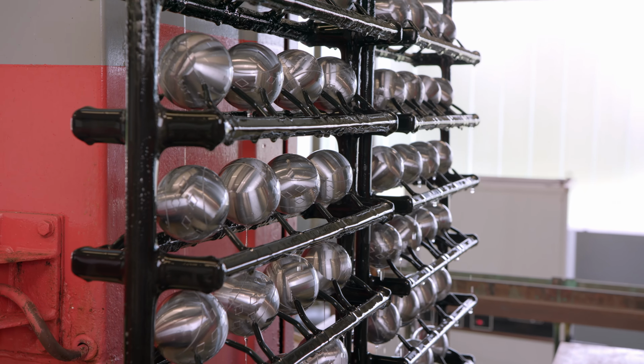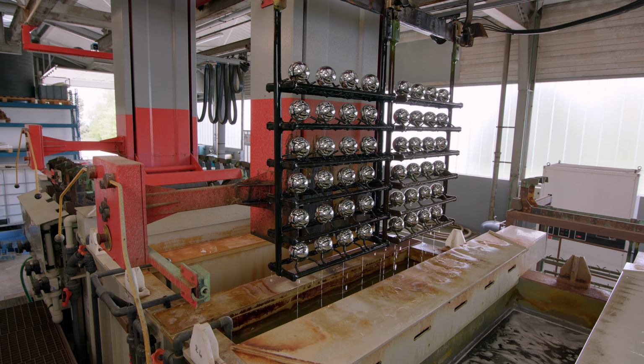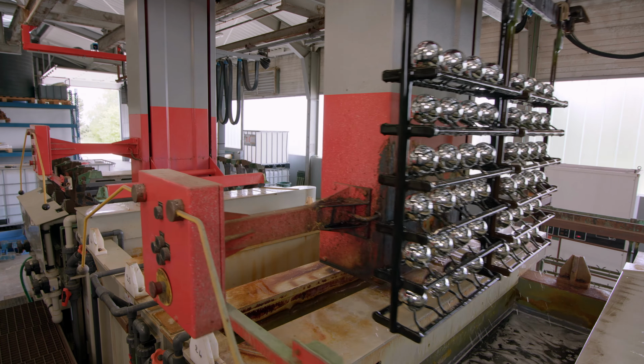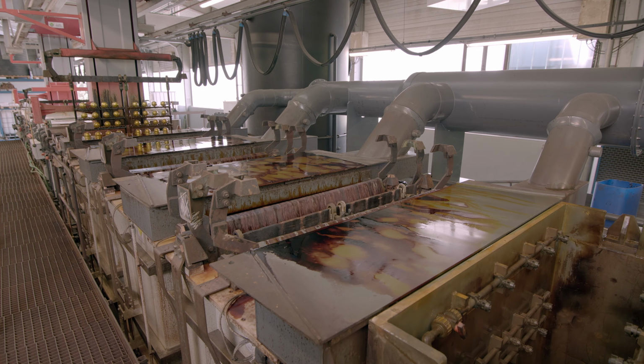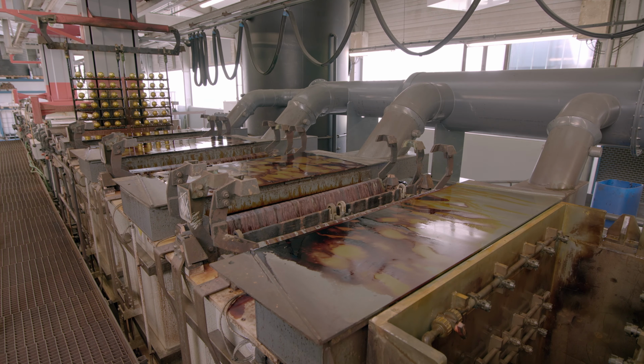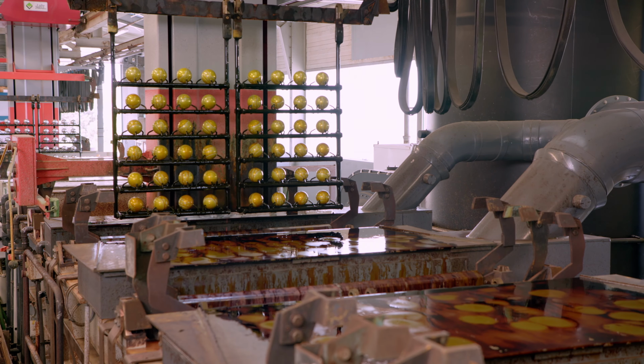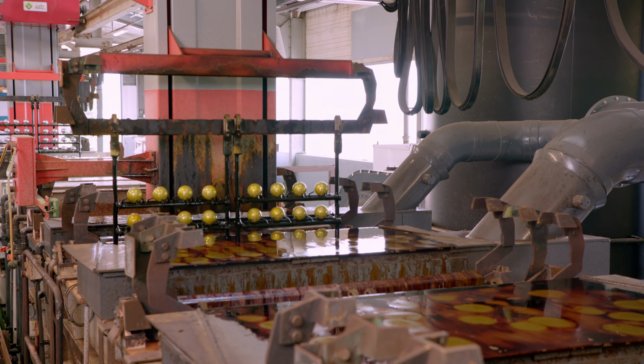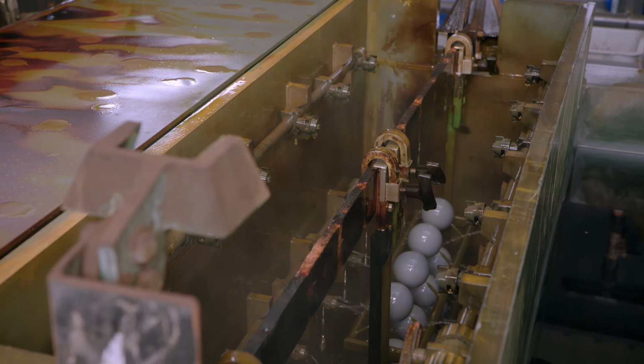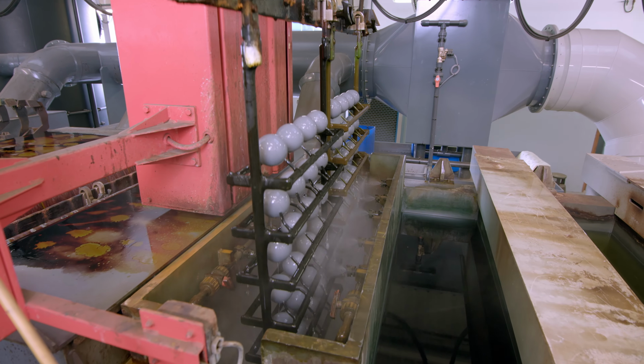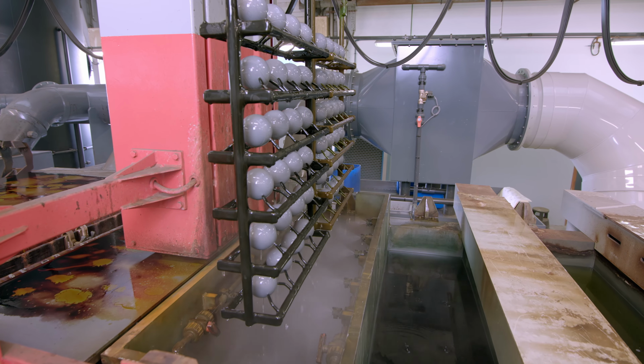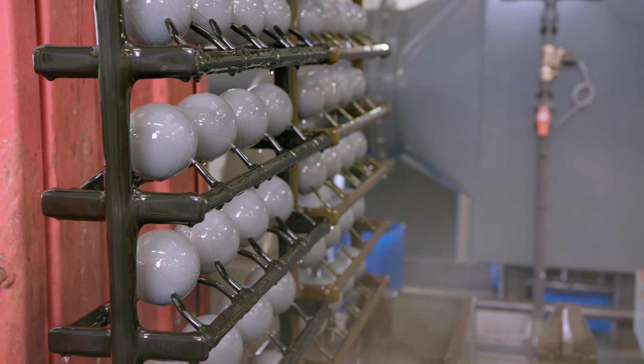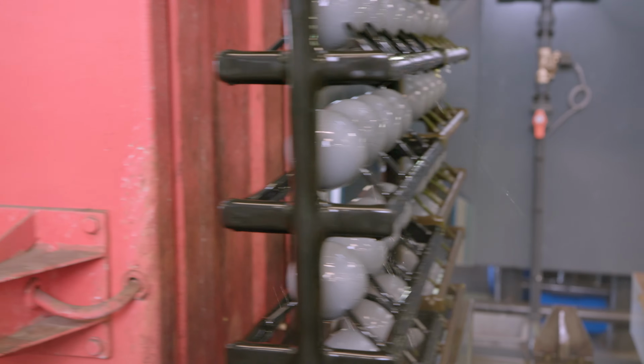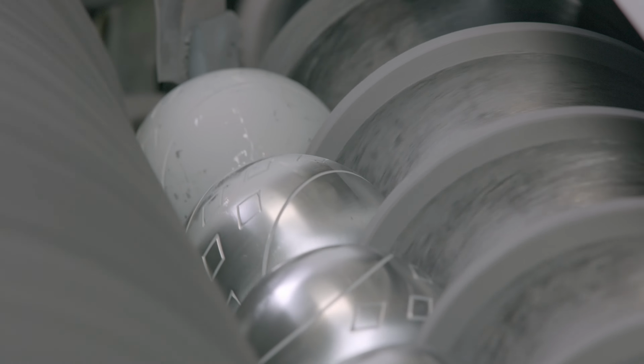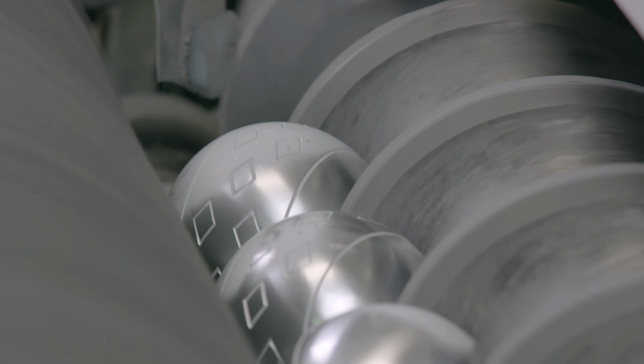To prevent oxidation and corrosion, the factory electroplates its carbon steel balls with a protective layer of chromium. It submerges the balls in a series of chemical baths and water baths to prep the surface for the final dip in an electroplating tank, in which an electrical current draws chromium particles through the water and deposits them onto the ball's surface. The chromium treatment leaves a white film. This brushing machine removes it and restores the shiny finish.